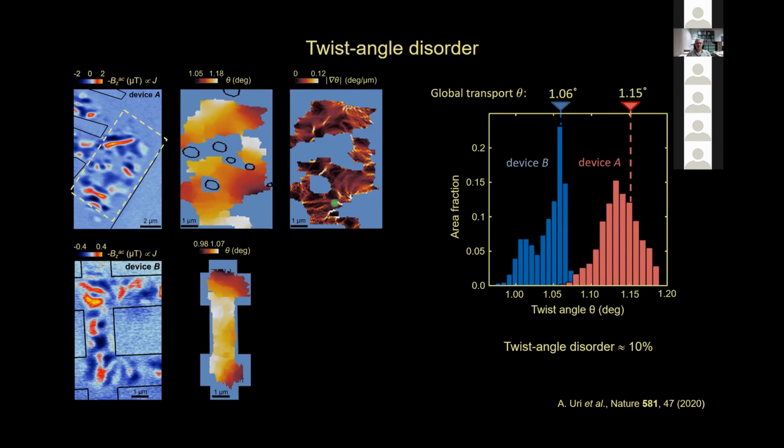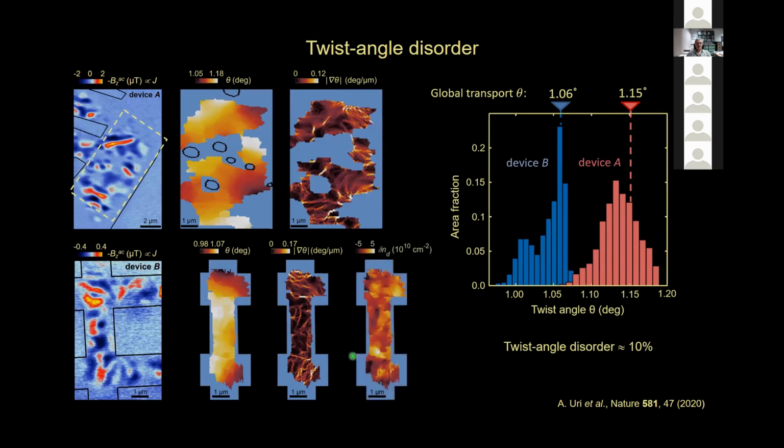between these neighboring parts of the mosaic structure, if you want. If we look at this sample, we get a very similar structure. Again, rather uniform areas with a fraction of a micron in diameter, separated by a network of stacking faults across which the twist angle changes quite abruptly. We can also extract the charge disorder, but I will not have time to describe it.